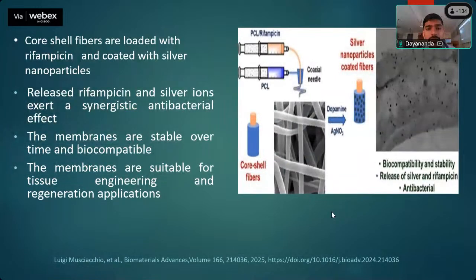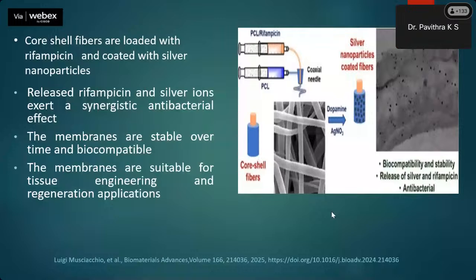This was another work, where again a core coaxial electrospinning strategy was used. Here the fibers are loaded with rifampicin and coated with silver nanoparticles. Rifampicin is a known antibiotic, particularly effective in inhibiting gram-positive bacteria. This releases rifampicin and silver together for a synergistic antibacterial effect, stable over time and biocompatible.